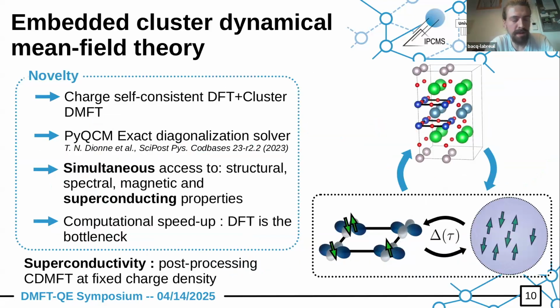Okay. So what is special to what we have implemented is that we have implemented it in such a way that we can do charge self-consistent DFT plus cluster dynamical mean field theory, right, with a 2x2 plaquette, so to get the d-wave, and so to be able to describe the d-wave superconductivity. To be able to take care actually of superconductivity, we use an exact diagonalization solver developed by David Sénéchal in Sherbrooke. And this allows, let's say, 2 main points. So, of course, to reach the superconducting regime because it works at 0 temperature. And this enables us to have a simultaneous description of the structural, magnetic, superconducting properties, but even structural properties within the framework of Kohn-Sham.